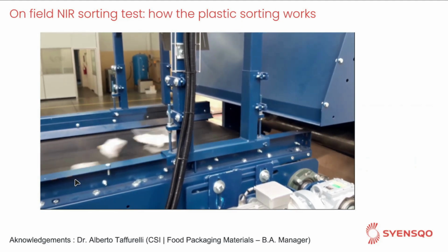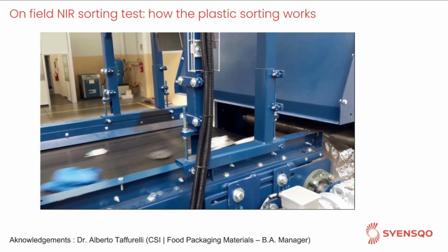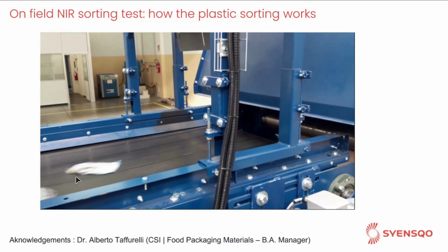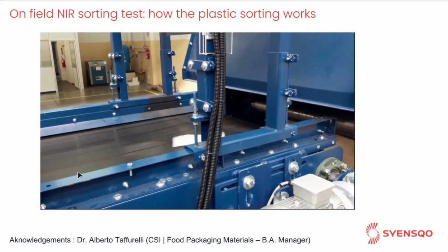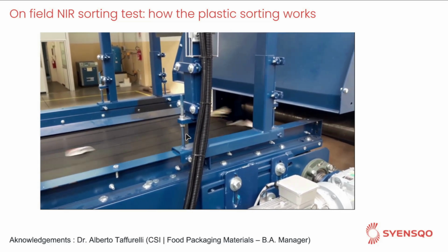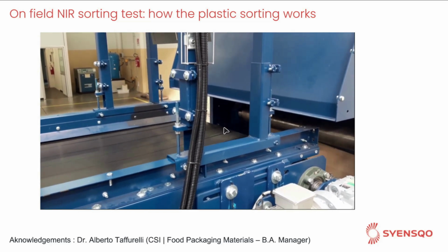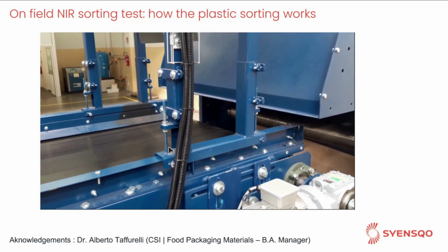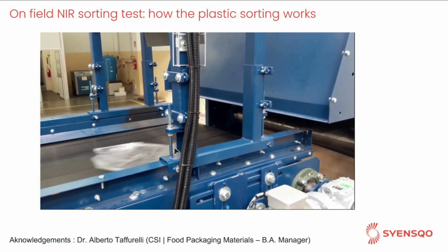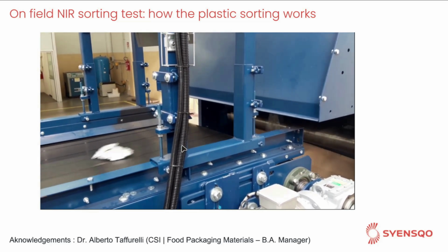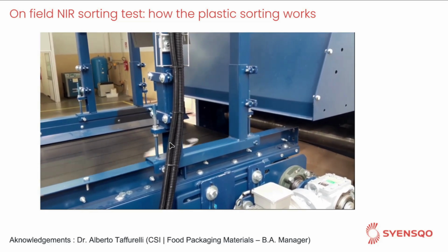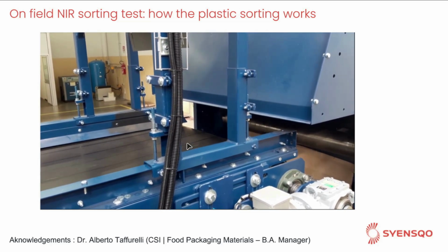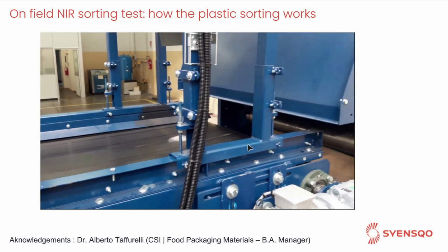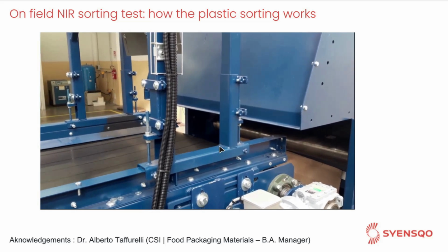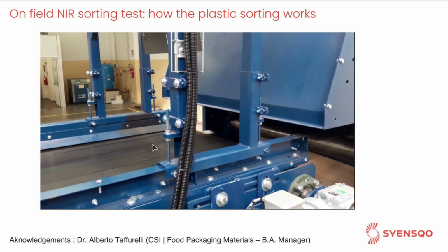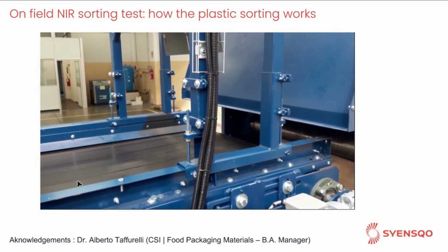Now I would like to show you how it works, which is quite interesting. You can hear also some noise here, which are the air jets, and now I put the audio off. You can see a lighter line half a meter before the end of the conveyor belt, and this is the region where the near-infrared sensor works. And after a fraction of a second, around 300 to 400 milliseconds, the air jets that you heard before choose whether to send upstream or downstream the object that passes through the sensor line.